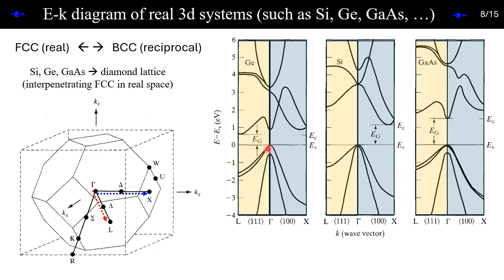The reason is that not only do you have to increase the E, you also need a shift in k. Electrons need enough momentum transfer. If you shine only light, that's not possible, because you don't have enough momentum from light or photons. How you can work this out, we'll give as an exercise problem. That's why you need phonons. So this is always a phonon-assisted process.